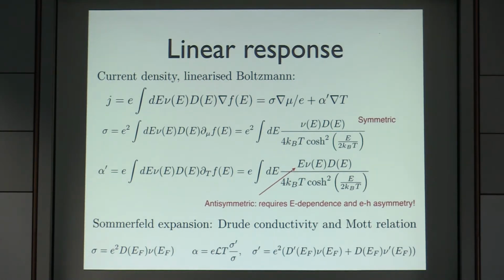The theory usually proceeds by making a linear response from the linearized Boltzmann equation. This is something that you have in, for example, Ashcroft-Mermin. From there, you can calculate the different coefficients, basically the conductivity and the thermoelectric coefficient. And what you notice is that the thermoelectric coefficient can be written as an integral over some quantity where you have the density of states, the diffusion constant, and energy.